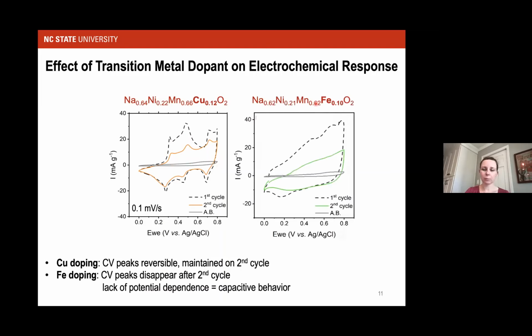However, if we had something like the iron containing material, there was a significant difference between first and second cycles. The CV peaks that are present here and here, they essentially disappear. And what we are left with is a cyclic voltammetry response that is very much potential independent. And that's essentially a capacitive response. So we had this transition from potential dependence to independence, depending on the transition metal layer composition.